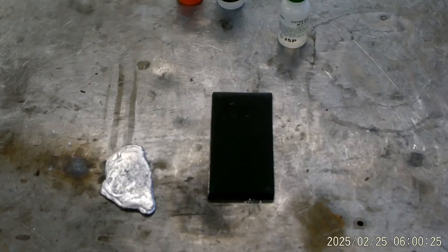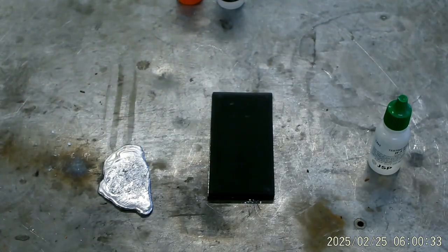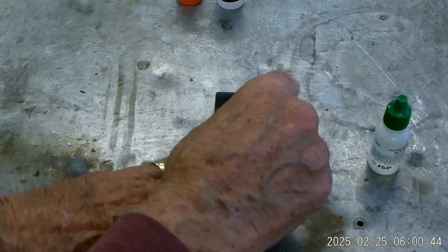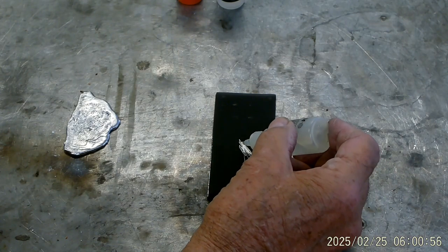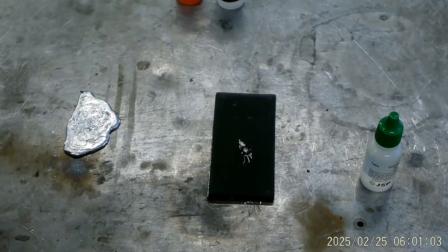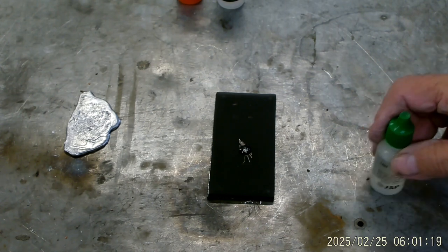I thought I had 10K but I don't see the 10K — I've got a 14K. We'll try 14 and see if we can get there. This is the acid. And if it goes all the way through, that means it's less than 14 karat. And it's not — so it's staying right there at 14K. It's 14 karat gold.